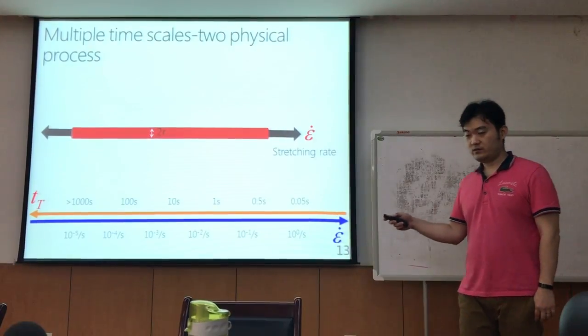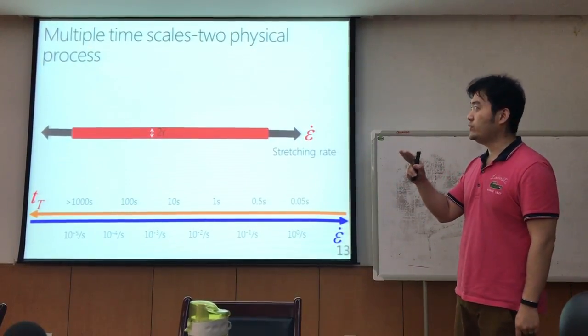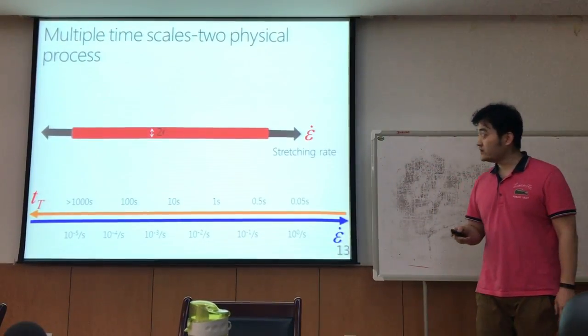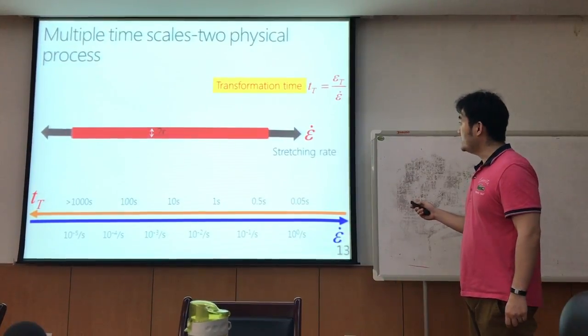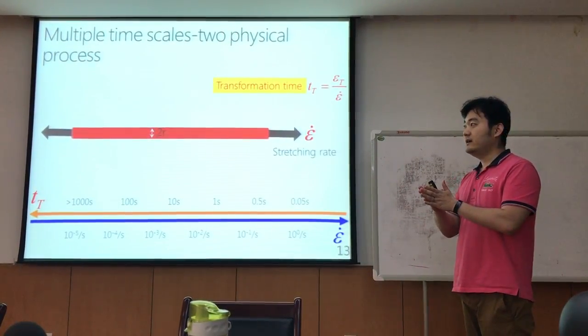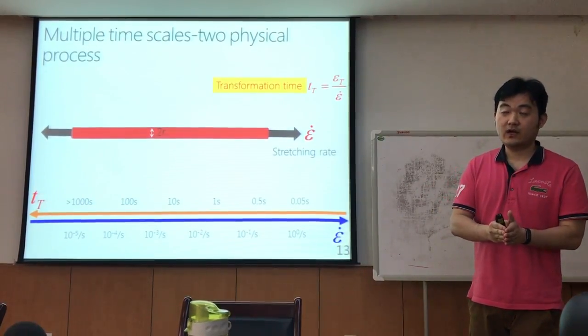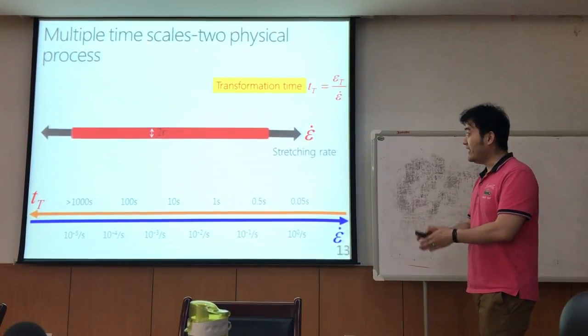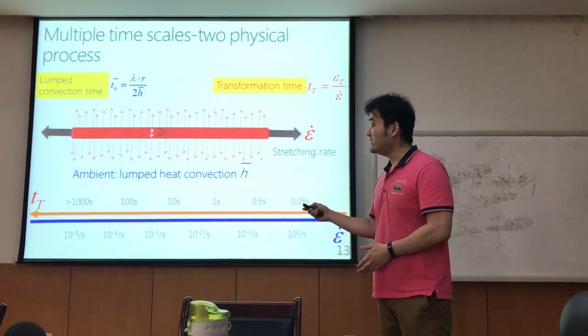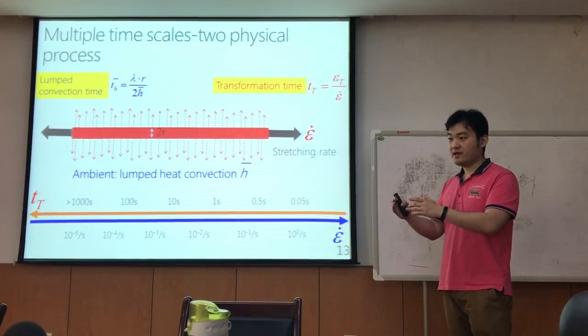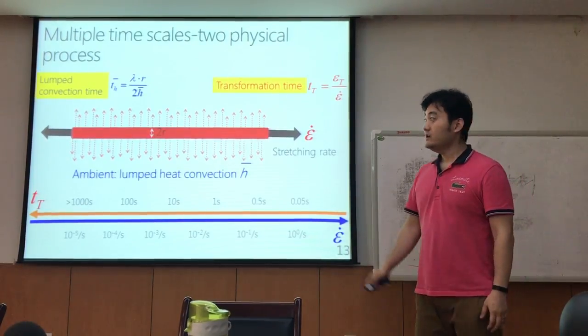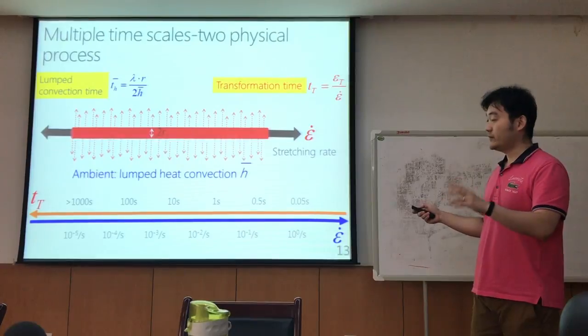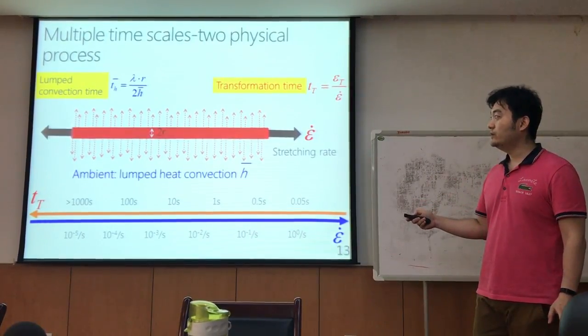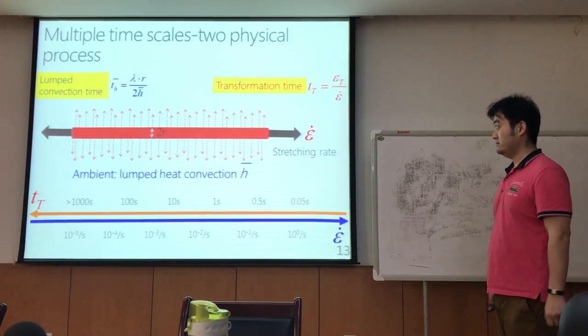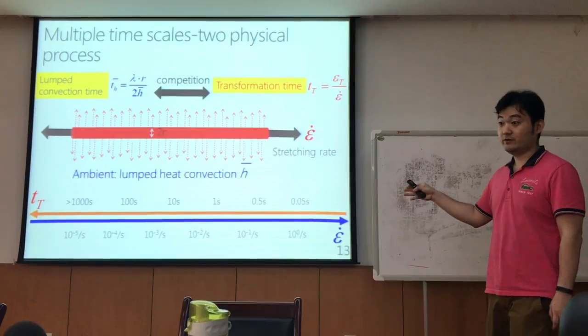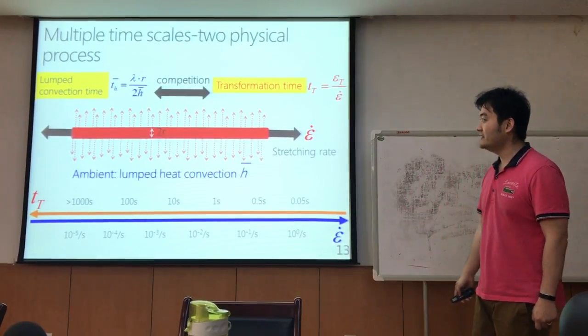And we find out during this process, two important time scales are involved. The first one is the transformation time, which characterizes the heat release or heat absorption time of the latent heat and hysteresis. Another time scale is the lumped convection time, which characterizes the ambient condition. So these two time scales have opposite effects on the temperature of the specimen. So they compete with each other. So what is the competition result? This is what we need to find out.